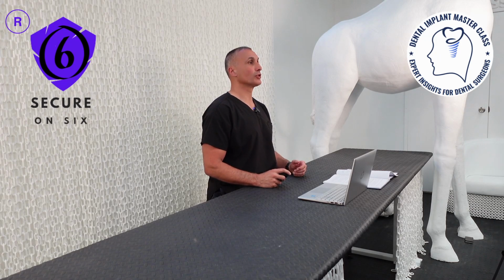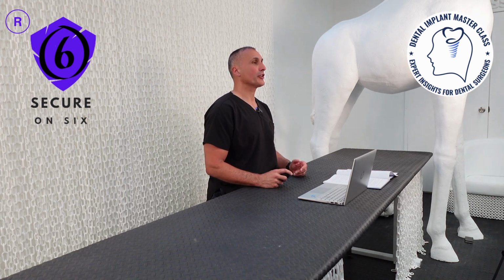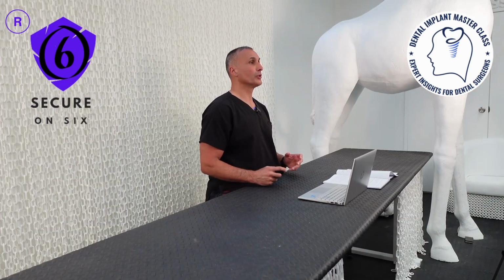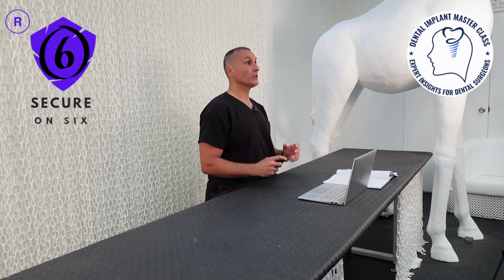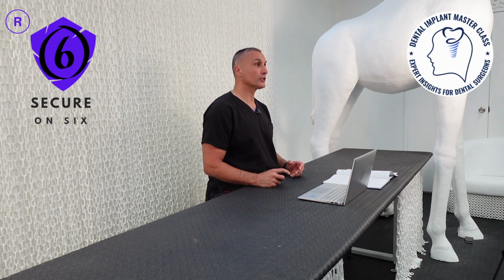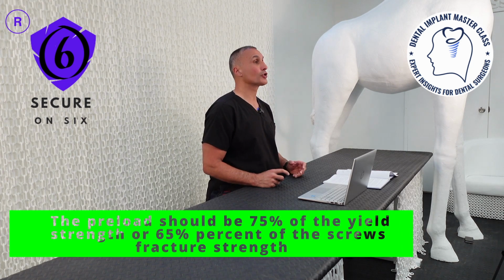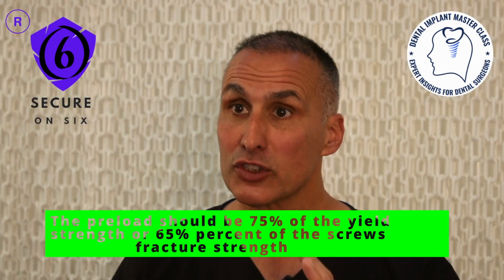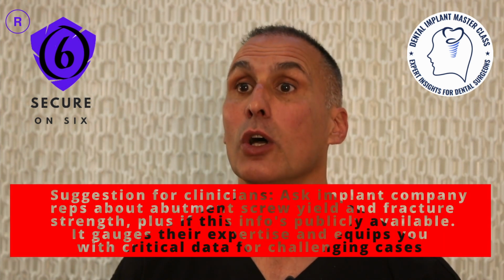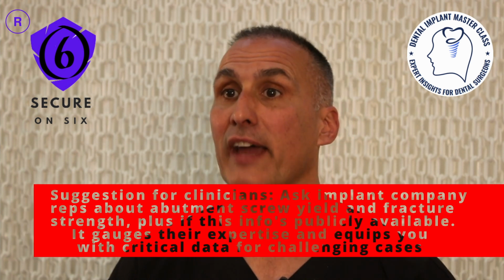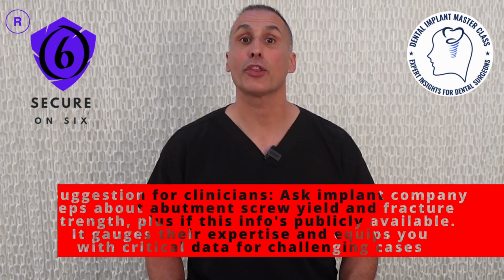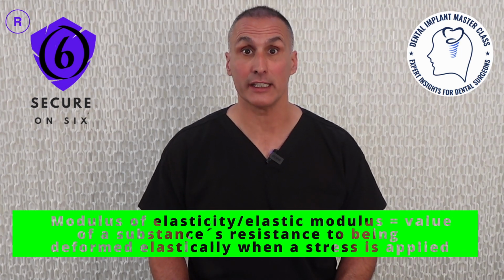Ziprick in 2018 mentioned that the preload force of an abutment screw depends on factors such as friction, thread pitch, and tightening torque. Krishan in 2014 noted that the optimal preload for a screw is reached when it elongates until it reaches capacity without exceeding the yield strength. In an ideal scenario, the preload should be 75% of the yield strength or 65% of the screw's fracture strength. Preload primarily depends on the applied torque and secondarily on factors such as component materials, screw head and thread design, and surface roughness. Screw strength is closely related to the modulus of elasticity of the screw material.